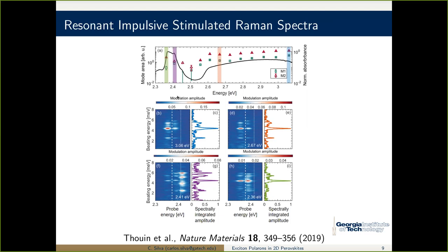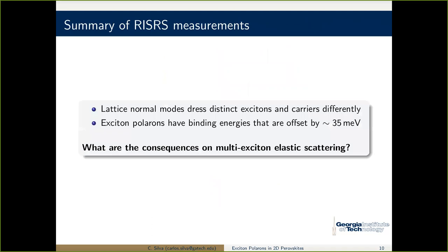But now we excite resonantly exciton B. Now we see that the activity is around the maximum of exciton B. And now the intensity distribution of this is, again, completely different to the photocarriers, but completely different to exciton A. So exciton A and exciton B perceive the lattice very differently to each other and to photocarriers. They are dressed by the lattice in a very distinct way. If this was a vibronic progression, this would not be the case. So they're distinct excitons, with different lattice dressings, with distinct sort of motion dressing them. So that's what comes out of this. What that allows us to say is that the lattice normal modes dress distinct excitons and carriers differently.